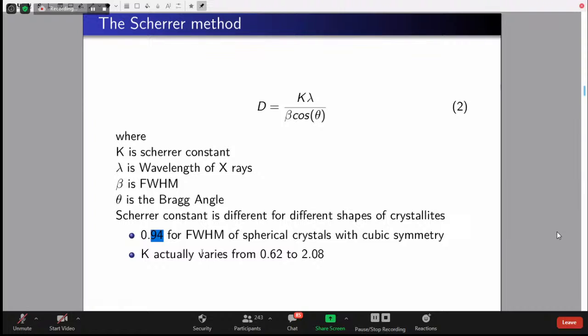Better you can go for the Williamson-Hall plot, where monoclinic is going to give you a large number of peaks, and if you put all of them in one, you will get a better average crystallite size rather than from the Scherrer formula. The Scherrer formula is more suitable for materials with cubic symmetry, like simple cubic, FCC, BCC. That much only we can go. Okay, sir.